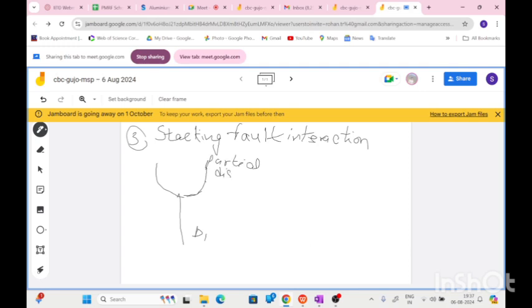Third is the stacking fault interaction. You know about the stacking fault, how it forms? A stacking fault forms when the Burgers vector of a dislocation splits into two parts. If the first initial dislocation has Burgers vector B1, it splits into two parts. These are called partial dislocations, so the Burgers vectors of these are B2 and B3.